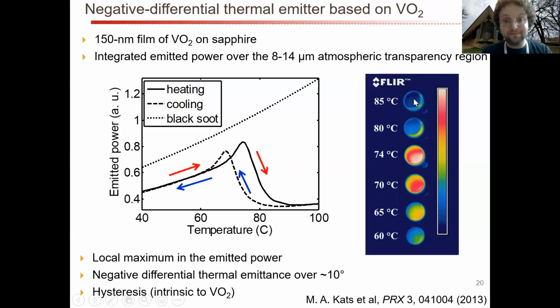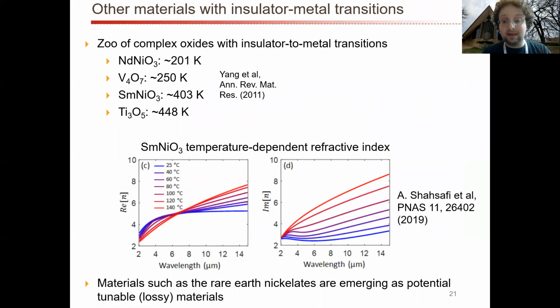And so when I moved to UW-Madison in 2015, we were quite excited to get started on playing with other types of phase transition materials to do similar type of engineering of thermal radiation. In particular, we focused on the zoo of complex oxides with insulator-to-metal phase transitions that have been explored by our collaborators at Purdue and Shriram Ramanathan's group. For example, these nickelates, these vanadium oxides, and so forth. Each one of them has transitions at quite different temperatures. You can look at these temperatures and realize why VO2 is so commonly used: the transition is very close to room temperature, which is quite nice.